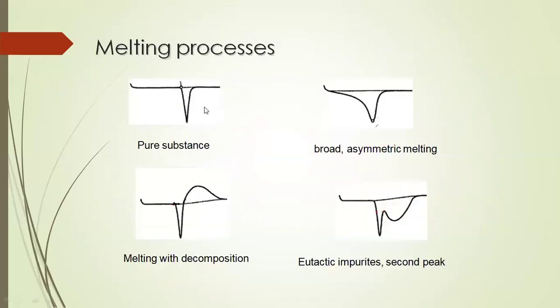This is how a melting process looks. If you get a sharp melting, as for a metal, that is a pure substance, you can say. In polymers, we get this type of melting, broad asymmetric melting, because we have different molecular weights. So lower molecular weights melt first, higher molecular weights stay, and we record this as the melting temperature of the polymer and this as the melting range of the polymer. If you get melting like this, it is melting with decomposition, which is a very bad scenario for DSC. This again shows that there are impurities in my material.